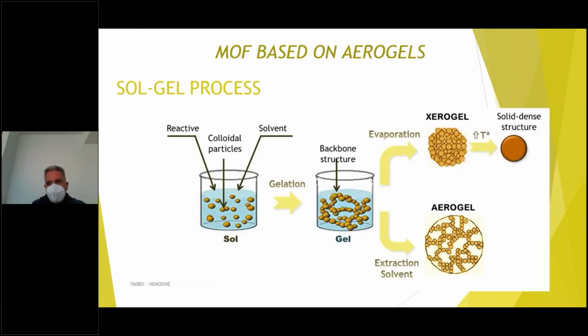We can dry the hydrogel with different processes. The most typical process is evaporation, for example, in an oven. If we do this, we collapse the system. We lose all the small, nanometric cavities, and we have a typical compact material that is named xerogel. This xerogel is not suitable for the application that we are talking about.